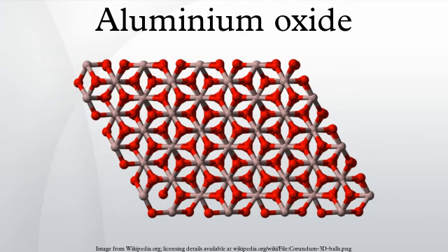For its application as an electrical insulator in integrated circuits, where conformal growth of thin film is a prerequisite and the preferred growth mode is atomic layer deposition, Al2O3 films were prepared by the chemical exchange between trimethyl aluminum, Al(CH3)3, and H2O: 2 Al(CH3)3 + 3 H2O → Al2O3 + 6 CH4.